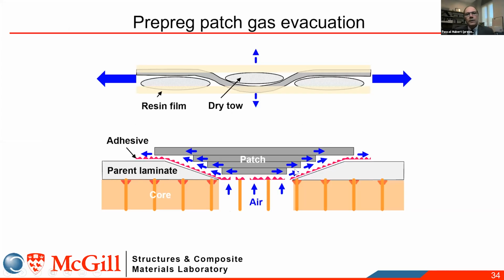So in a repair, this is what you're doing. You have a parent laminate that has a damage. You take the damage out, so you scarf, and then you put a patch. The patch can be pre-cured, or you can co-cure the patch on the part. And then we put an adhesive layer. So the challenge here is to really try to remove all the air from that patch so that you have no porosity at the bond line.